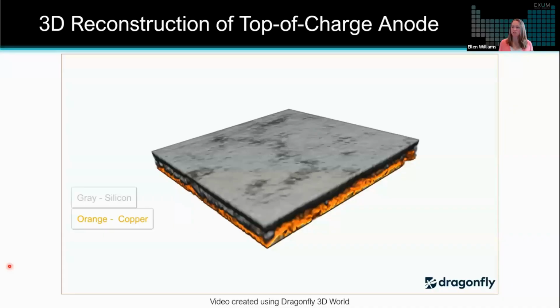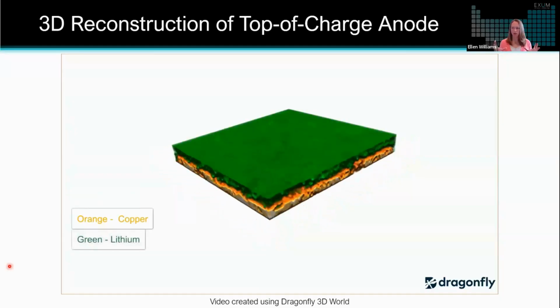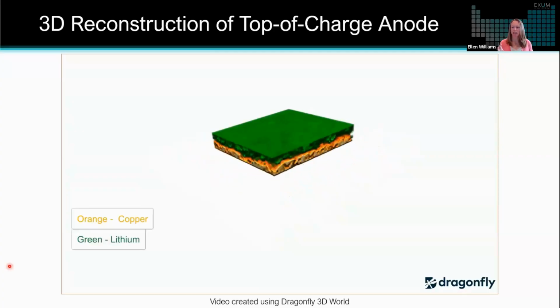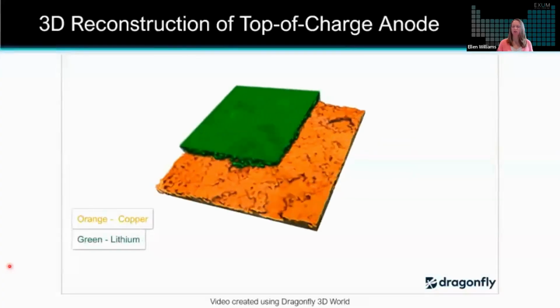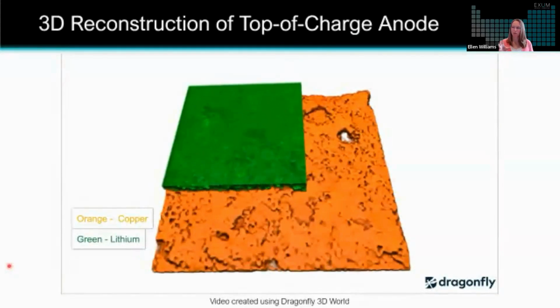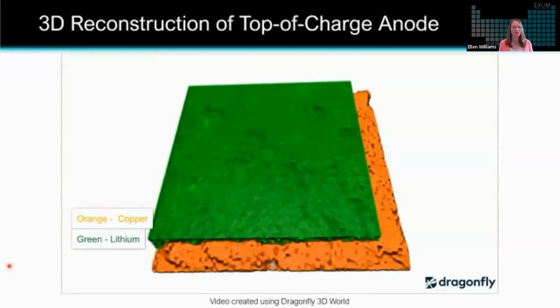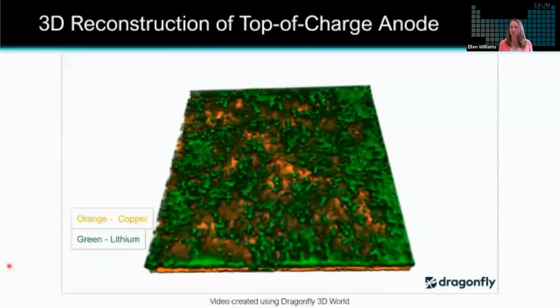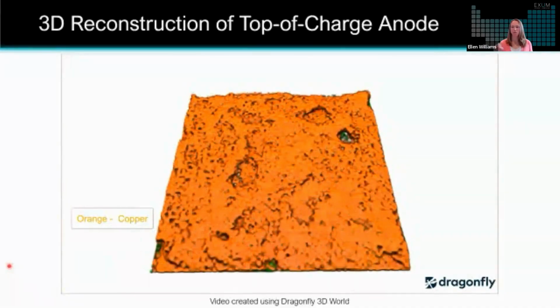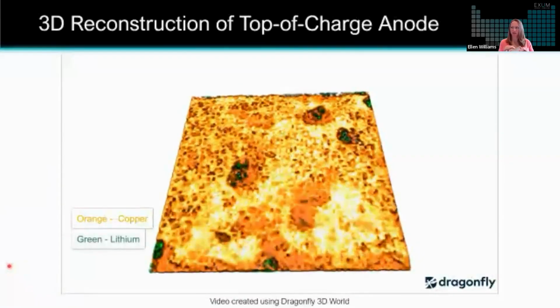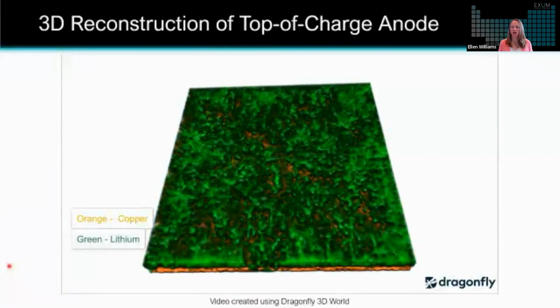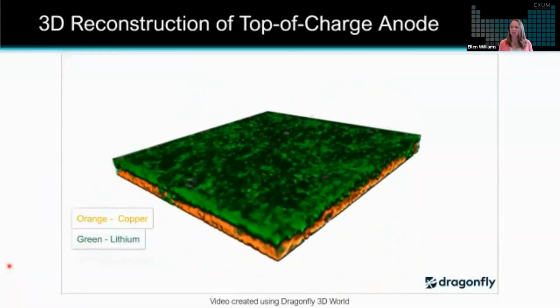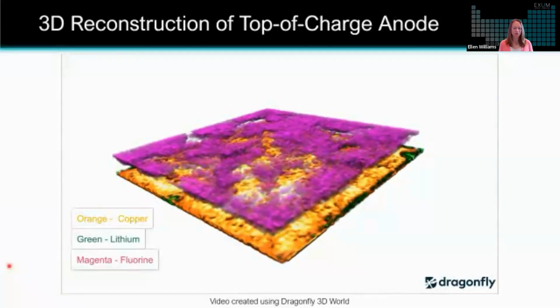And I want to point out that this visualization was done with Dragonfly 3D World that some of you may be familiar with. And so again, what we're looking at here is that top of charge anode where we see that copper current collector on the bottom. And specifically, we're most interested in how is that lithium distributed that we see in green. And we can see fairly uniformly distributed within that cross section. We see that there is a little bit of surface heterogeneity on the copper current collector where we're seeing those lithium pockets. And then we did identify fluorine.